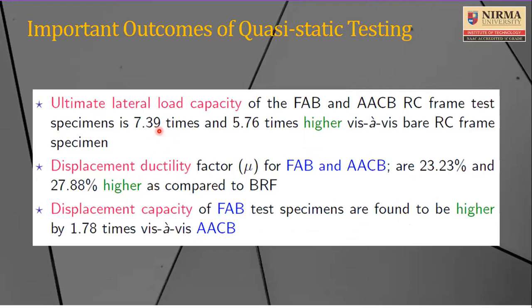These are some of the important outputs, which I am not reading, but just to show you that fly ash brick and AEC block based RC infill panels take almost 7.39 times and 5.76 times higher lateral load as compared to the bare frame, and the ductility capability is also of the order of 20% higher, and the displacement capacity of fly ash brick is about 1.78 times higher than the AEC block based RC panel. So one can understand that both types of masonry infills are good as compared to the bare frame, and we must consider their lateral load capacity in seismic analysis.